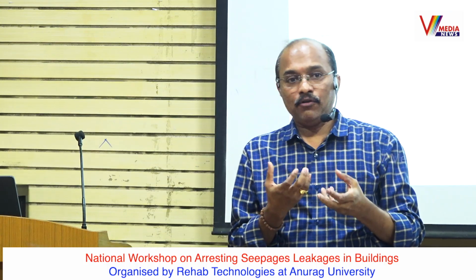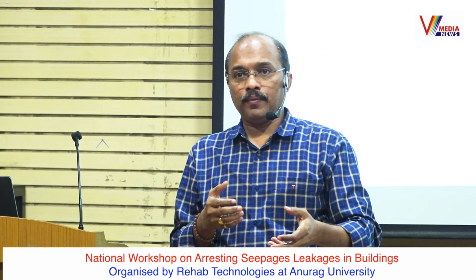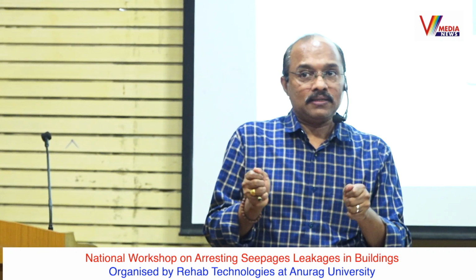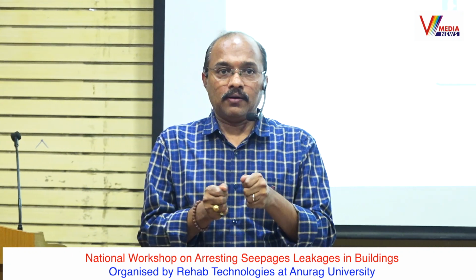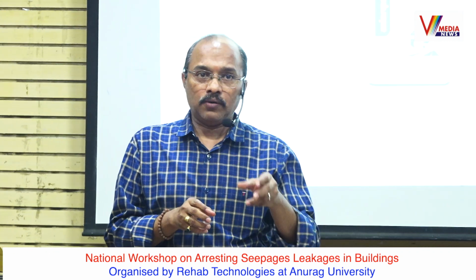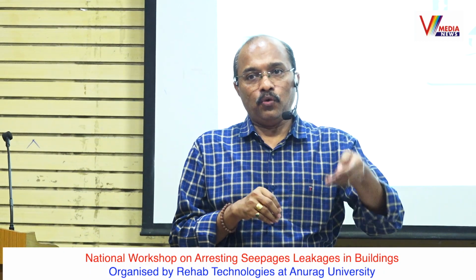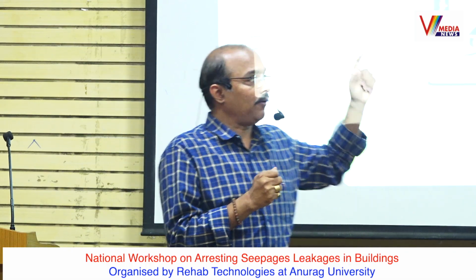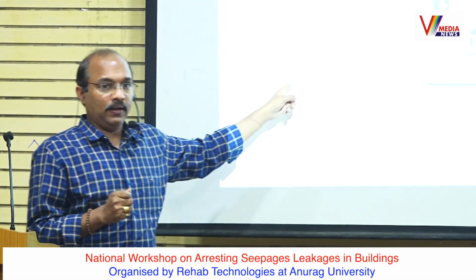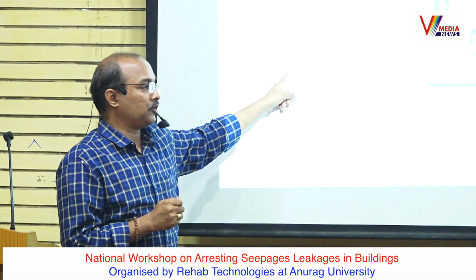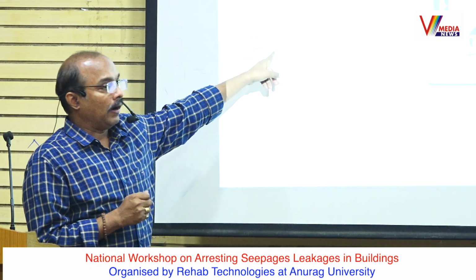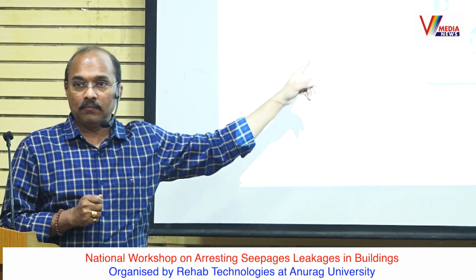These shrinkage cracks have to be treated. Speakers prior to me were talking about structural cracks. I am not talking about structural cracks. The cracks I mean are shrinkage cracks, plastic cracks or other cracks that come onto the structure. So you just do one thing: widen the crack, pour this material, it will flood into the concrete and strengthen those areas. So this is a very, very important material in engineering, especially in the repair and restoration segment and the waterproofing segment, and it is to be used.